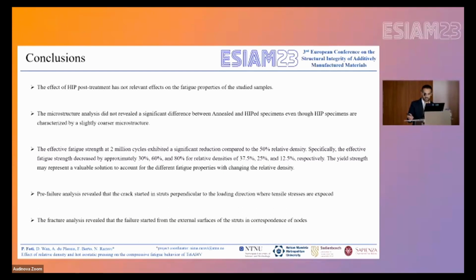And we have seen that there is quite a huge difference between the effective fatigue strength of the 50% relative density and the 12% relative density, but as we have shown, the yield strength may represent a valuable solution to account for the different fatigue properties with changing relative densities. And the pre-failure analysis revealed that the crack started in a strut perpendicular to the loading direction, where tensile stresses are expected, and the fracture started at the surface in correspondence with the nodes.